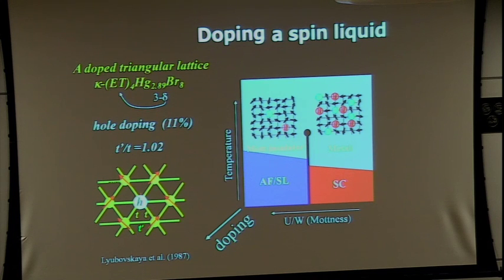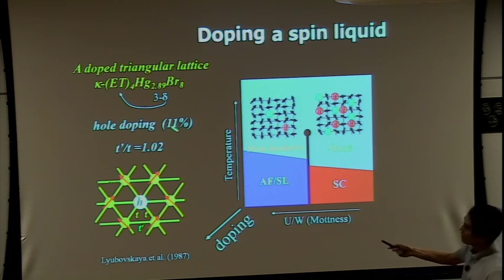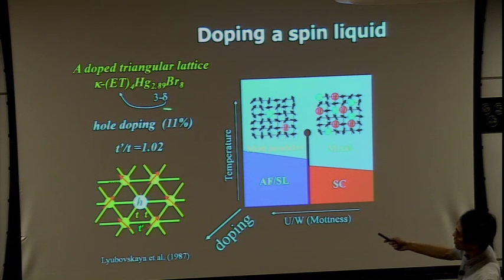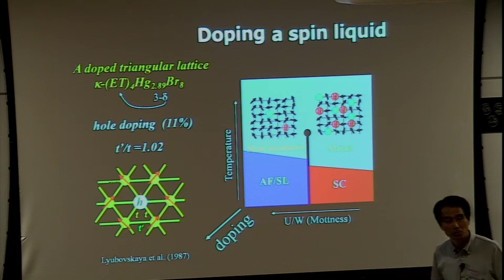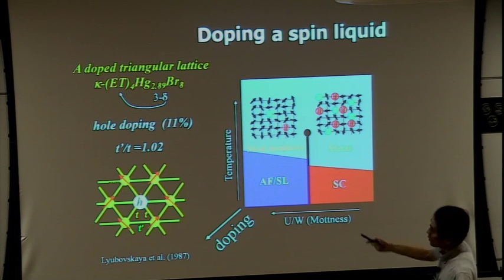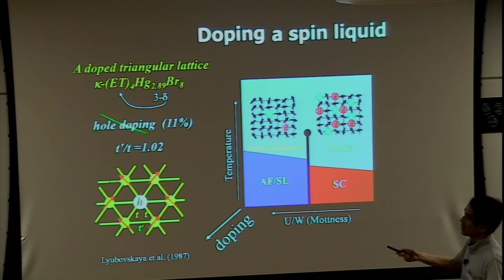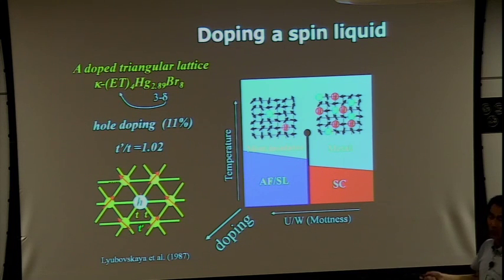However, there is an exceptional material we have. And that is this one, a copper-type material with similar structures. However, the difference is in the anion species, in the insulating species. Mercury 2.89, bromine 8. It's a non-stoichiometric material. It's very, very funny. We synthesized these materials and characterized the content. Always the mercury content is 2.89. So this is not accidental.